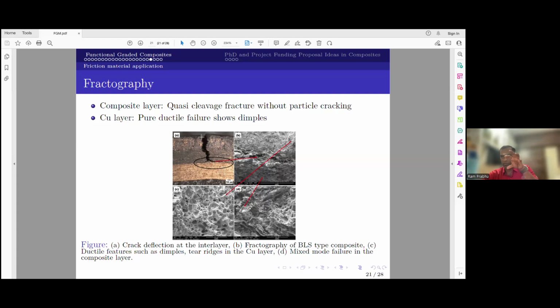And when we look at the composite region and the copper region failure, you can see a lot of dimples. Dimples are the typical feature of ductile fracture. In composite regions, you have both, like a quasi-cleavage: cleavage is there, dimples are also there. So composites fail by a mixed mode fracture, whereas the copper layer fails by the ductile mode. This shows that because I introduced the copper layer, it increased the toughness of the composites through macrostructure toughening mechanisms. So this is the proof for improving the toughness in addition to retaining the strength of your composites. In fact, it has better strength than the conventional composites.